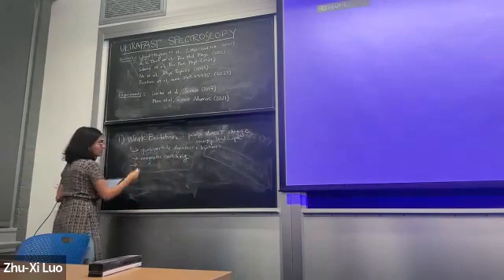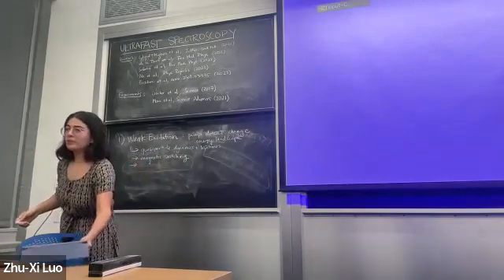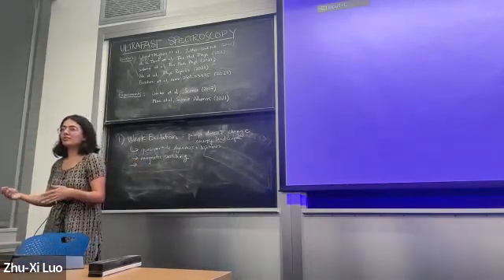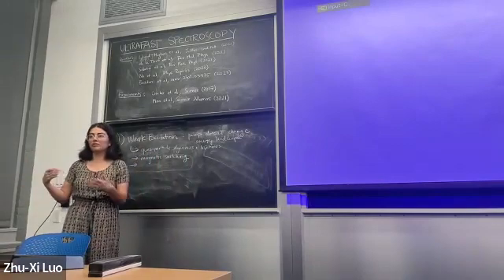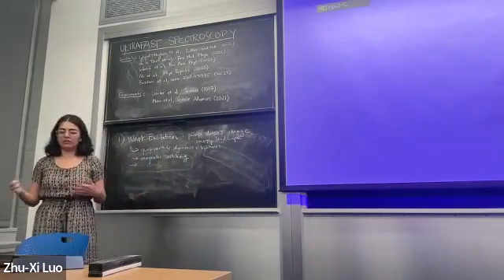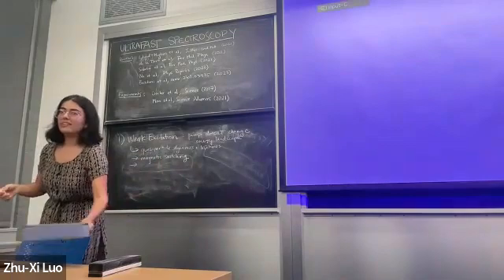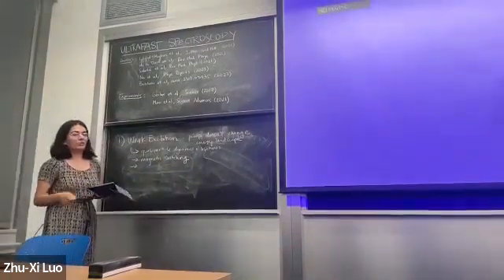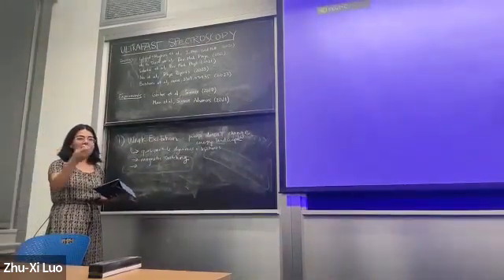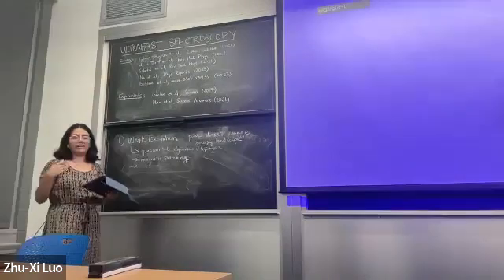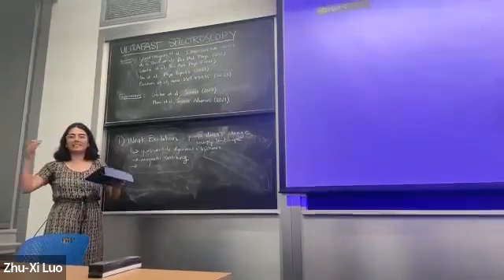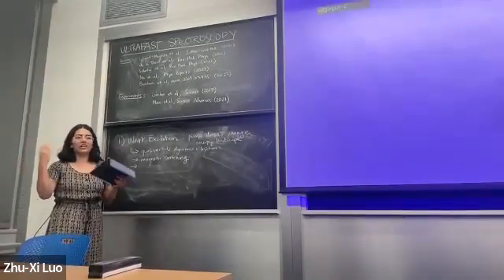And then also, of course, with equilibrium ARPES, you're limited to imaging states below the Fermi energy that are occupied in equilibrium. But this method, where we first excite our system and then we image the band structure, allows us to access higher energy unoccupied states.